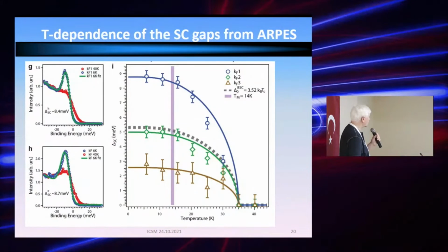So these are results on a larger scale. The important question is what happens in the vicinity of the magnetic transition, because we were motivated in these studies to see any deviation in the vicinity of the magnetic transition, to answer the question of how the magnetic ordering affects the superconducting pair. With this resolution, we do not see any impact of the magnetic ordering on the superconducting states.